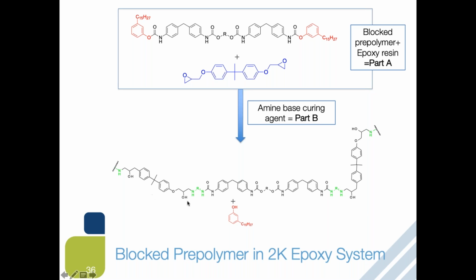So as you can see, the deblocked isocyanate will react with amine, especially at room temperature, therefore forming the chemically bonded system. And then the deblocked cardanol will stay in the system because cardanol is non-volatile, so it may act as, let's say, a plasticizer or diluent and another function based on your systems.